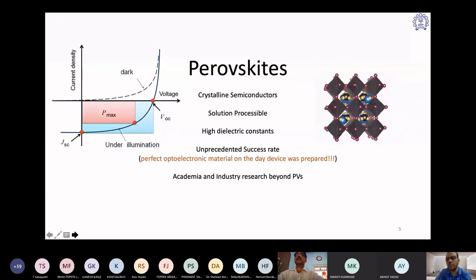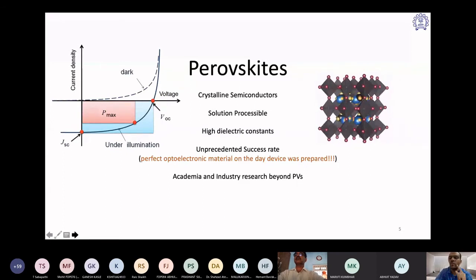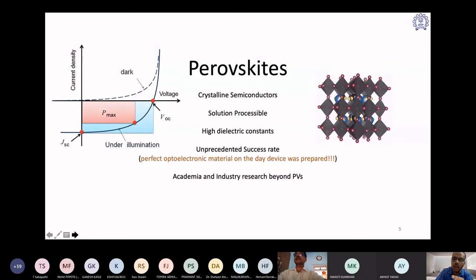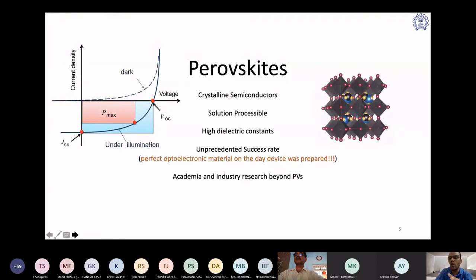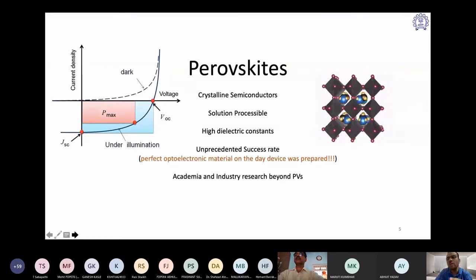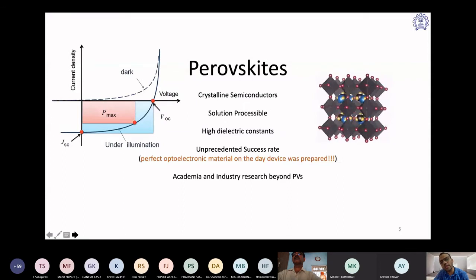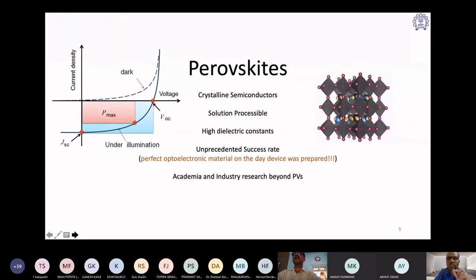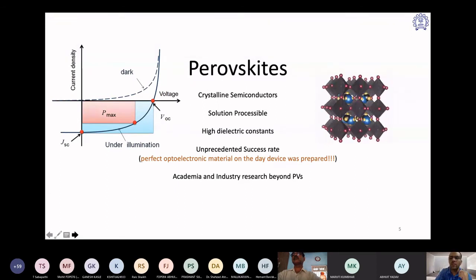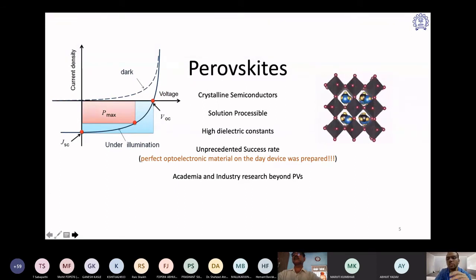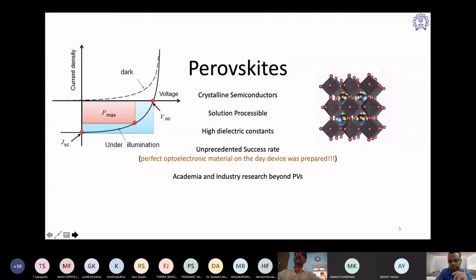Light has got an electric field and a magnetic field. It's all pointing vectors. So that electric field will basically align these ions in that open space of the octahedra. And once that methylammonium ion gets aligned with respect to the incoming light, it distorts the octahedra a bit, and that distortion introduces additional phonon-related effects, and lots of interesting photophysics takes place.